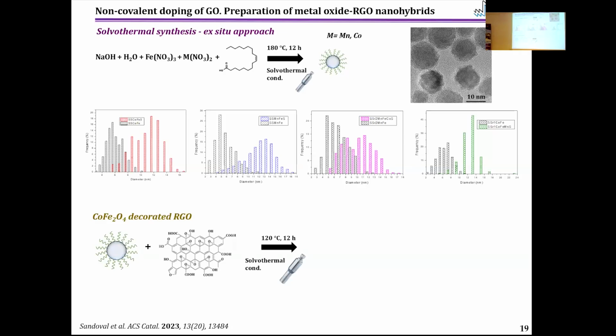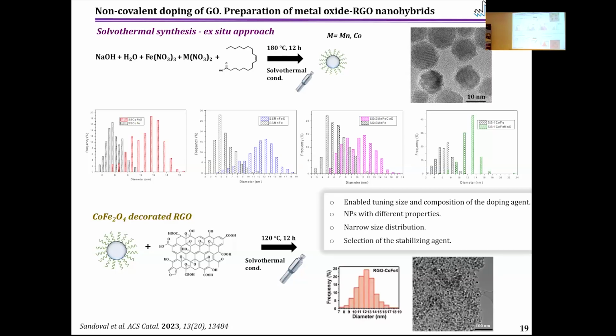So then, of course, I did the second step, which is also solvothermal, and this protocol enabled the tuning of size and composition. We can prepare, as I mentioned, nanoparticles with different properties. We have narrow size distribution, and we can also select the stabilizing agent. And this is also important because before attaching these particles onto the graphene oxide, we can interchange the stabilizing agent. And this provides the possibility of having particles which are dispersible in different solvents for different applications. As I mentioned, we made high-resolution TEM for the characterization. These particles are stable, have a very narrow distribution, and we also can tune the loading of the particles onto the graphene oxide by changing the amount of precursor we put into the reactor.